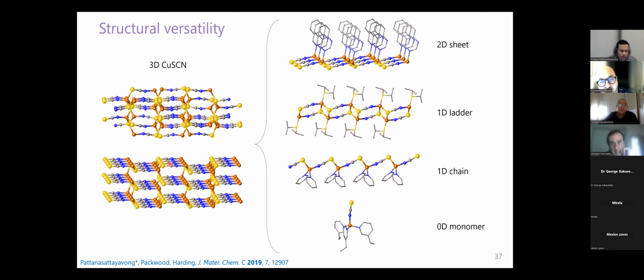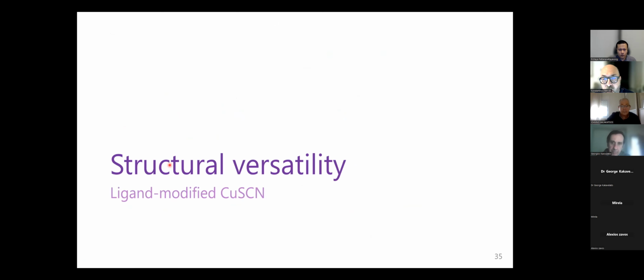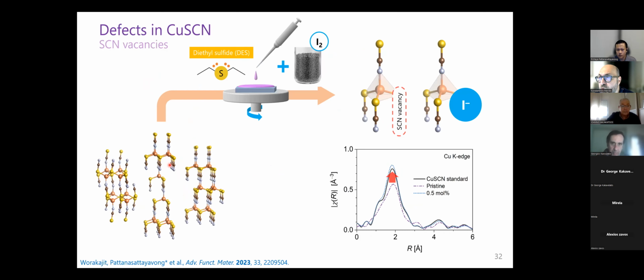And how do you think that they interact? Because they observed an electrical response sensor. So when they had the hydrogen, the conductivity changed, and when the hydrogen was removed, the conductivity restored back to its initial state. And I was wondering, in the case of the perovskites, we suspect that they interact with some vacancies. But in this case, you're right, the gas intrudes through the porosity of the material and interacts with the platform. But I was wondering what is the main mechanism of this sensing. When you were presenting, I thought that probably it was somehow an interaction with a vacant position of the ligand, but probably this is not the case.